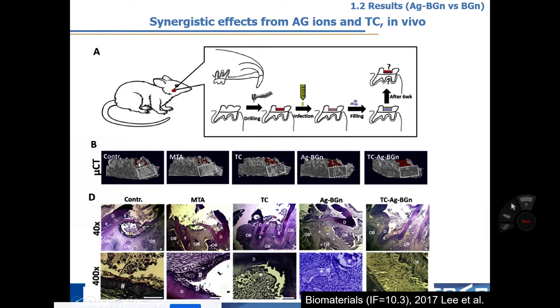As you saw before, the red color is regenerative dentin from the inside of the pulp chamber. So the TC-Ag-BGn has more red color, which means they have more regenerative dentin. And then when you look at the apical root side, the white one means that the alveolar bone surrounding your apical root area is all resorbed, which means it is all degraded. But in the case of TC-Ag-BGn, it is all sustained as a gray color.